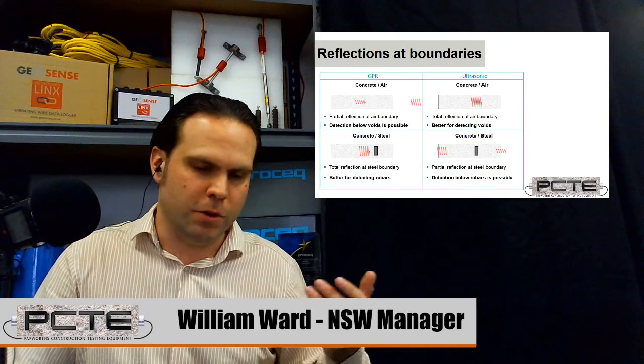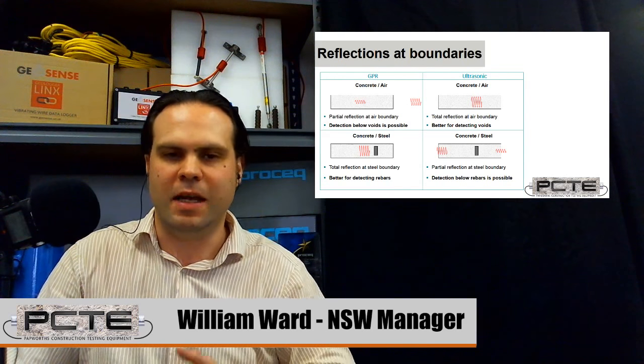But if you're choosing a technique and you want to locate steel, I would use a radar system. And if I wanted to locate damage or voiding, I would use an ultrasonic system. So, the generally recommended applications for radar is the location of reinforcing, and it's also very quick. They're a rolling scanning system, so you can pick up a lot of information very quickly. So if you need to survey structures quickly, radar's also a go-to.